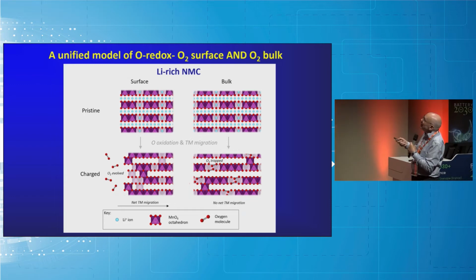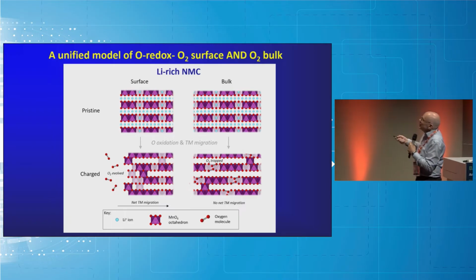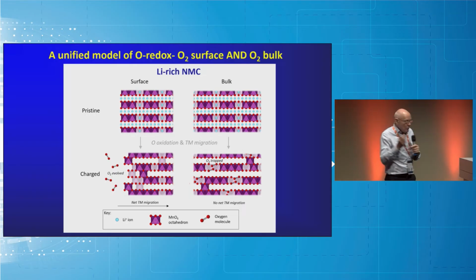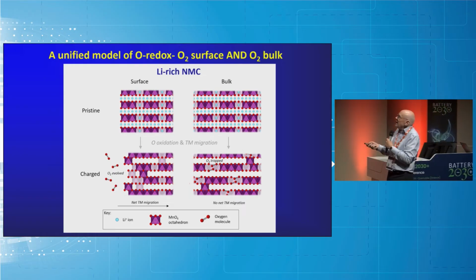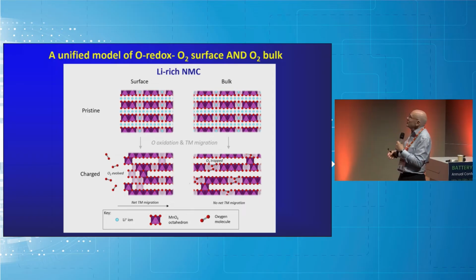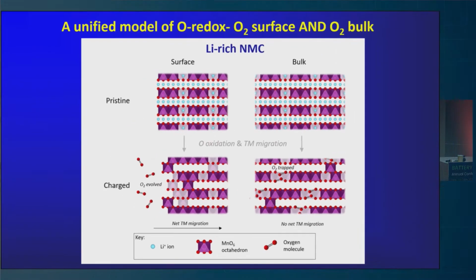So here's our cartoon of our pristine material again. This is the surface and this is the bulk, and of course it's the same when you start off. When you go through that oxygen redox, when you oxidize oxide ions, you lose oxygen at the surface. Probably the oxide ions form peroxide first and then O2, and then become evolved from the surface. As they do so, of course, the surface densifies. This has been shown before. You're losing lithium ions from this region. You're losing oxygen. You're densifying.